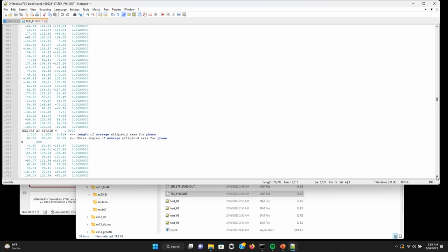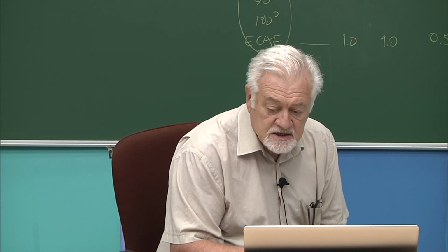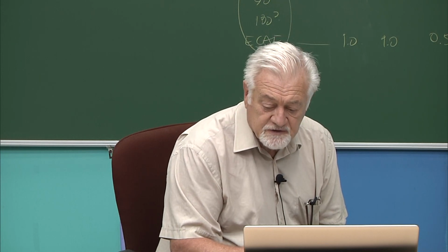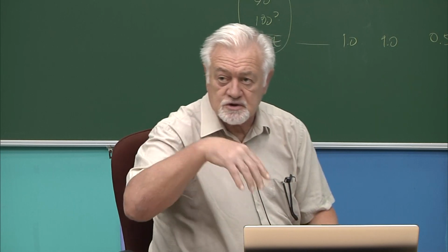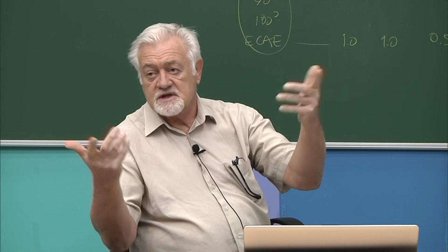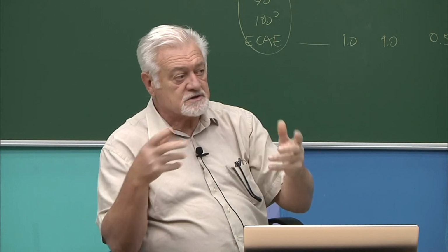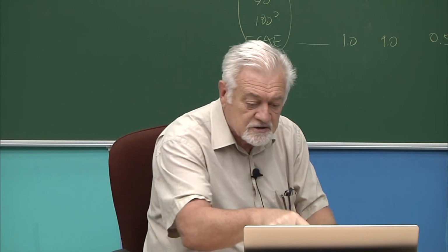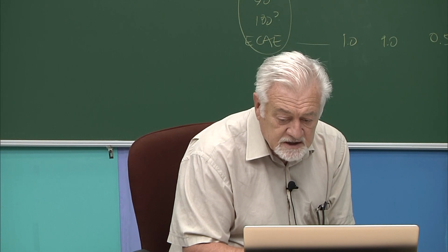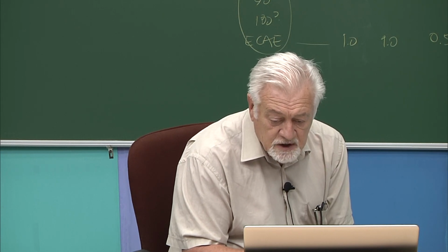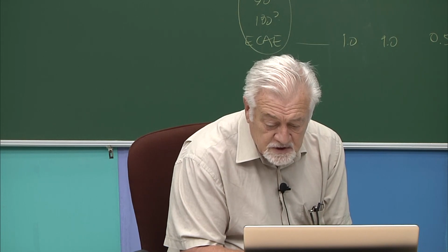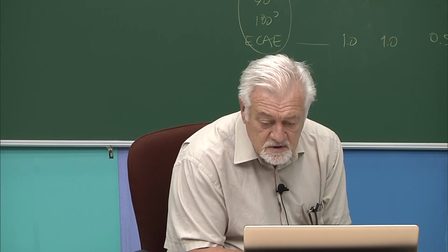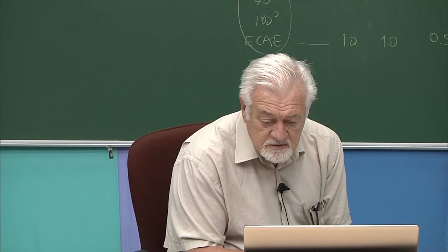By the way, the file has 104 lines. So these are two passes of 50 steps each. The first pass is the first equal channel angular extrusion, and then you do the rigid rotation, but there is no stress associated with that because you just rotate your sample rigidly, and then you do the next pass, and those are the stresses. Yes, if you look at the stress, I guess we are looking at the stress 1, 2, 0.28, 0.29, 0.26, 0.22. It has a minimum of 0.22.